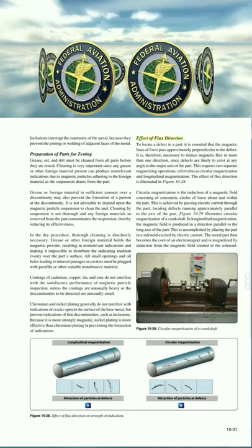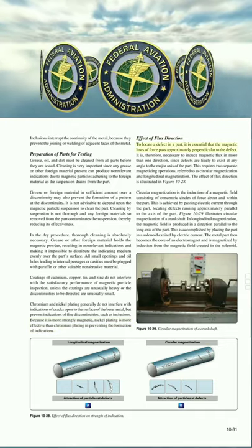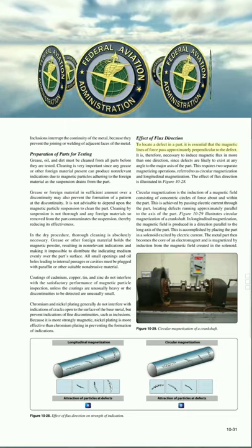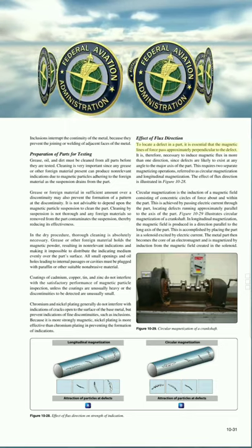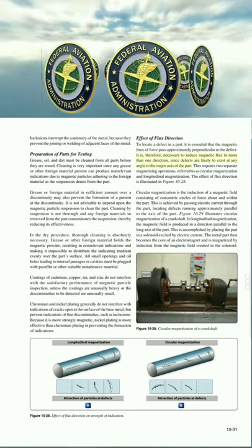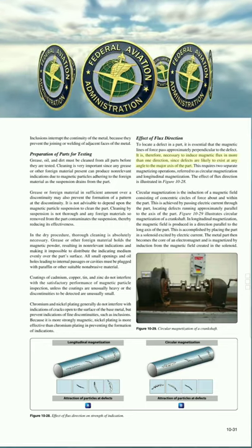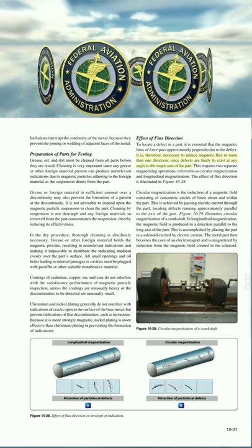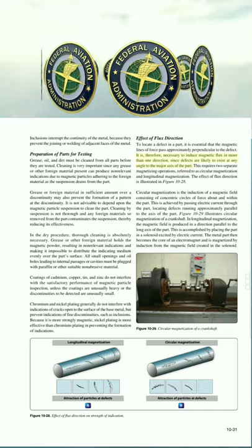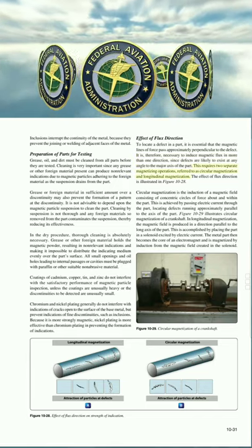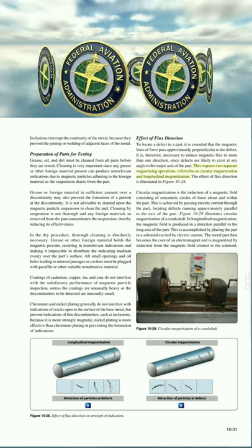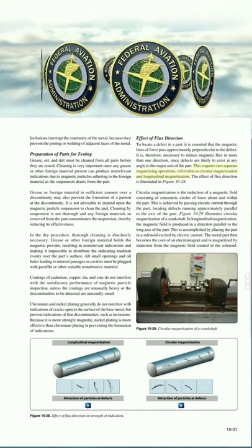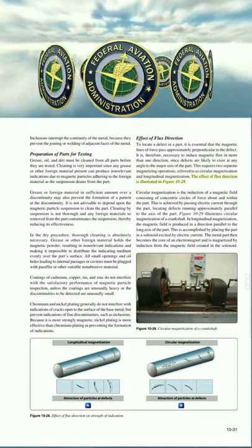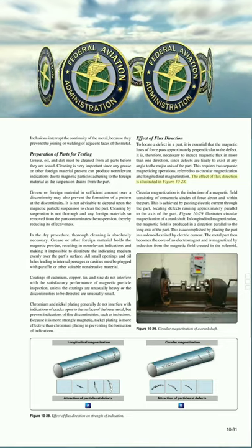Effect of flux direction. To locate a defect in a part, it is essential that the magnetic lines of force pass approximately perpendicular to the defect. It is, therefore, necessary to induce magnetic flux in more than one direction, since defects are likely to exist at any angle to the major axis of the part. This requires two separate magnetizing operations, referred to as circular magnetization and longitudinal magnetization. The effect of flux direction is illustrated in Figure 10-28.